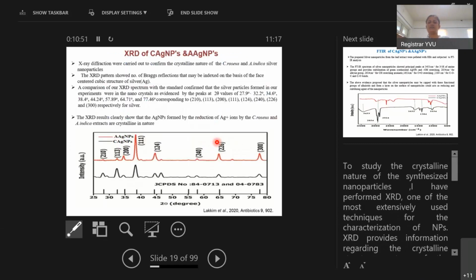After that, for studying the crystalline nature of the synthesized silver nanoparticles, I performed X-ray diffraction analysis. X-ray diffraction was carried out to confirm the crystalline nature. The X-ray diffraction pattern showed a number of Bragg reflections that may be indexed on the basis of the face-centered cubic structure of silver. A comparison of our XRD spectrum with the standard confirmed silver nanoparticle formation.